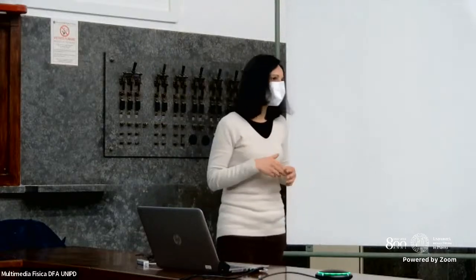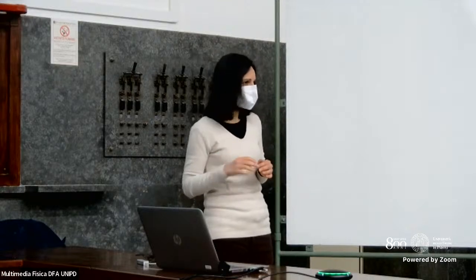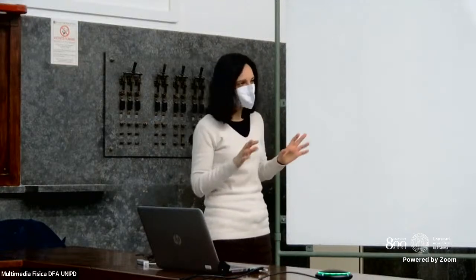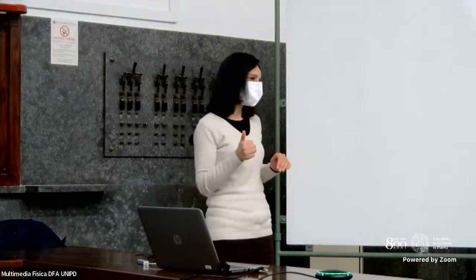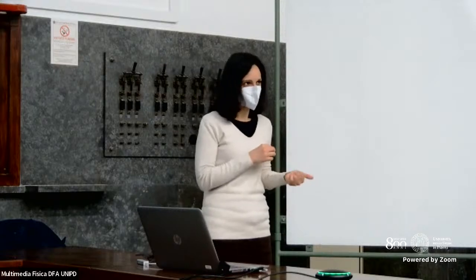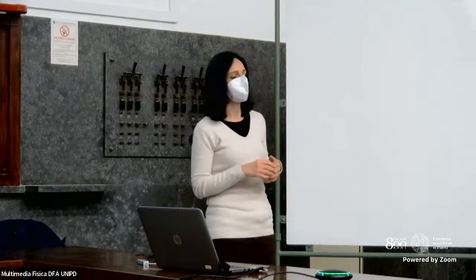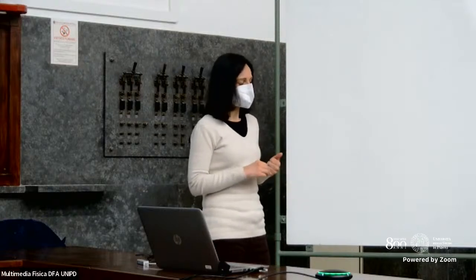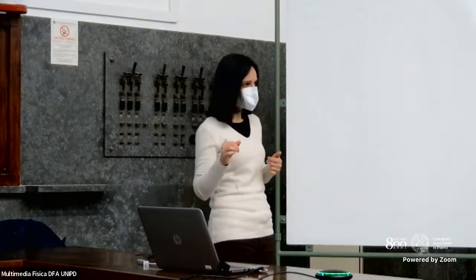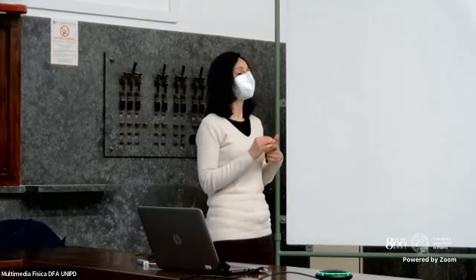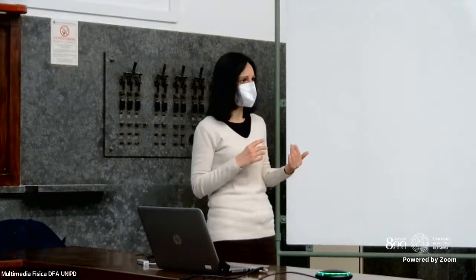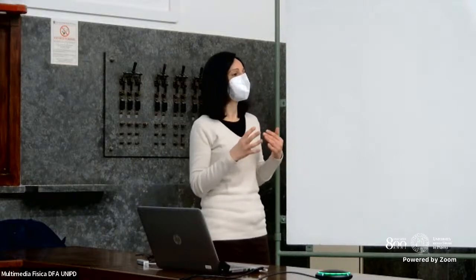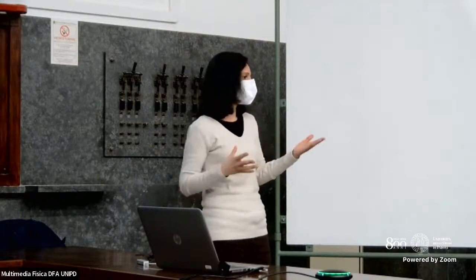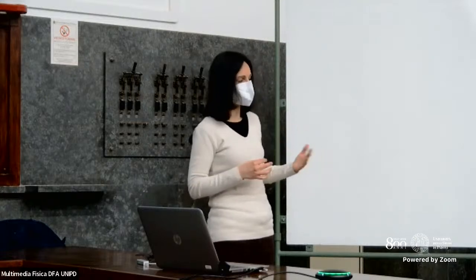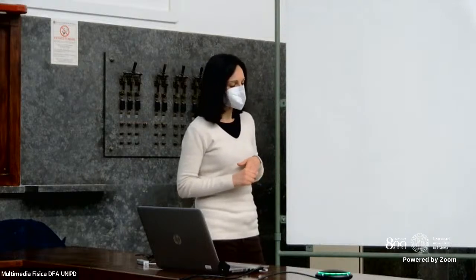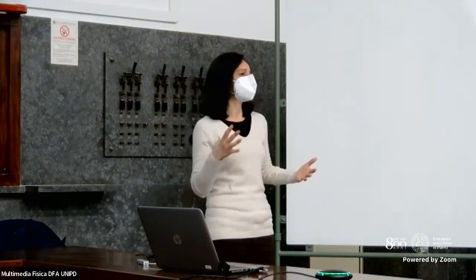Yeah, you can find in literature several possible solutions to this. However, the final numbers are one order of magnitude less with respect to inorganic materials. So one can apply an extra poling to the chains, for example, or one can build hybrid materials where you embed inorganic nanoparticles based, for example, on barium titanate. These are just a couple, but you can find many.